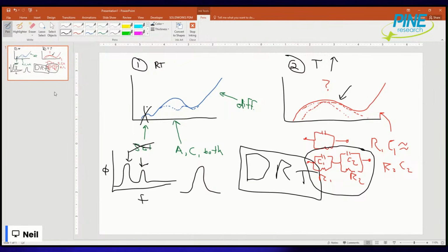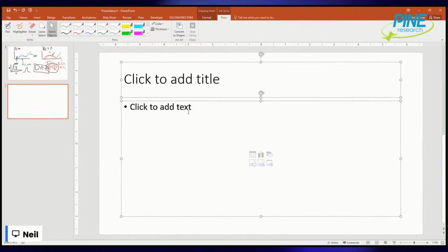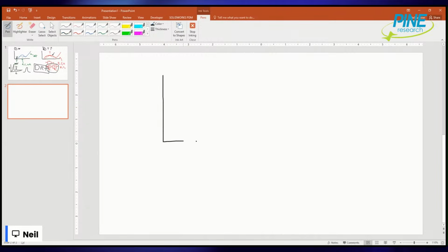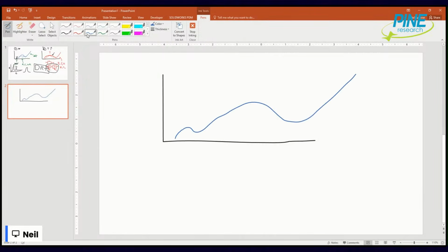You also would want to look at, as the temperature is increasing, these blue and red, I'll use the same colors to be consistent. So as my temperature goes up, did I start with this? Again, I'll just draw the same ones. And did I end up with this? That would be a good sign, which is to say that as the temperature increased, the semicircle, I got only one, but it's smaller. So my charge transfer resistance, my RCT at high temperature, is less than my RCT at low temperature.